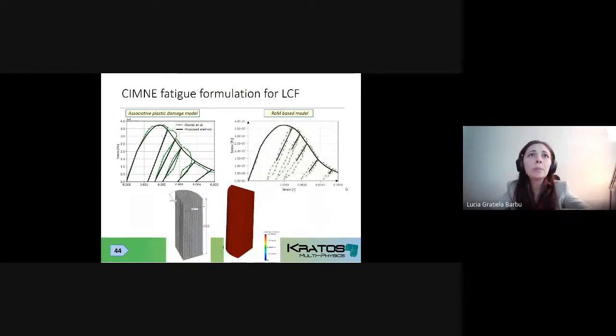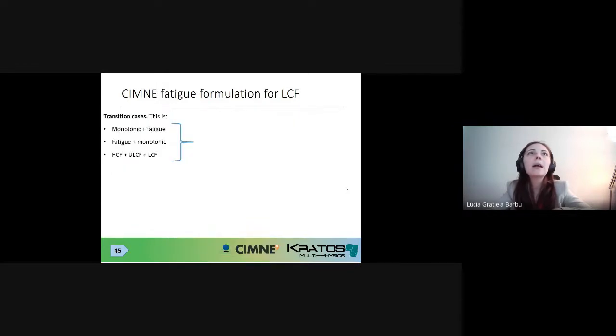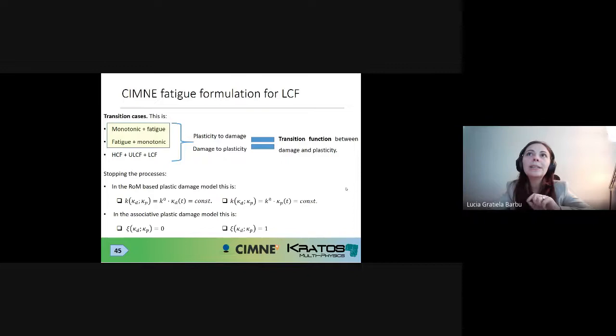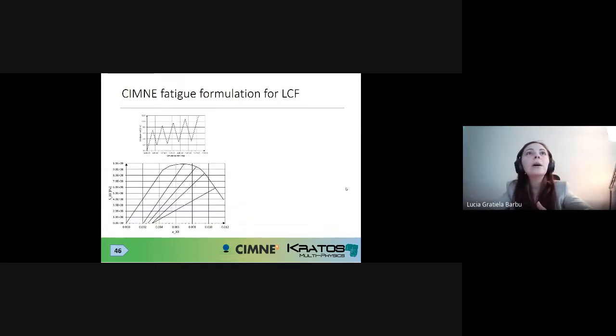Another case that we did, which was compressive behavior, again, a comparison between the associative plastic and rule of mixtures. I don't want to insist here again. But let's just say that we also need some transition cases, because as I said, it's important for us to be able to migrate from monotonic with fatigue, fatigue monotonic, or combinations of cyclic loading. This is why we need transitions from plasticity to damage, damage to plasticity, and we need specific transition functioning between these models just to make sure that we don't recuperate, we don't go back on the level of plastic strain, it's fixed, and we don't go back on the level of damage once we switch from a process to the other.